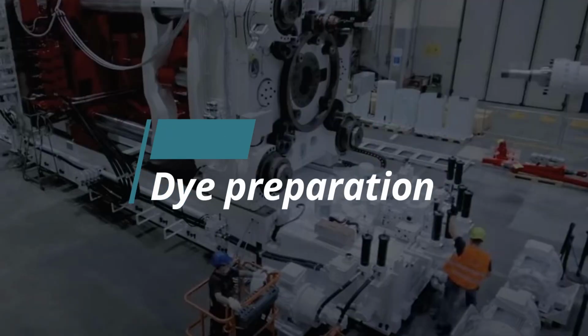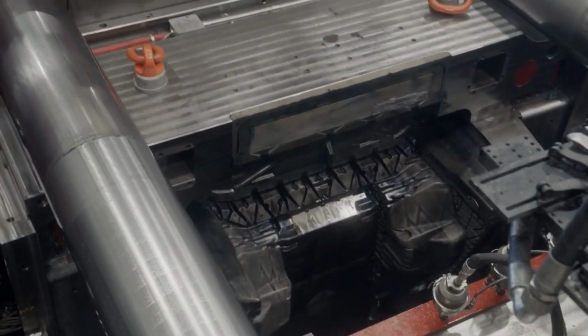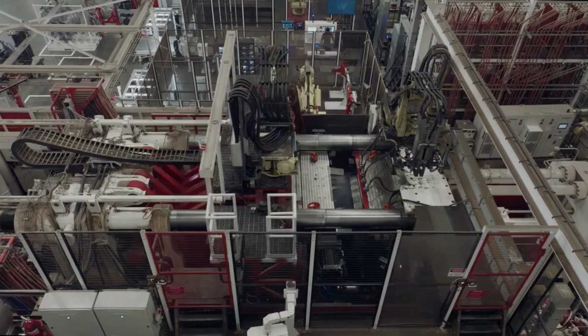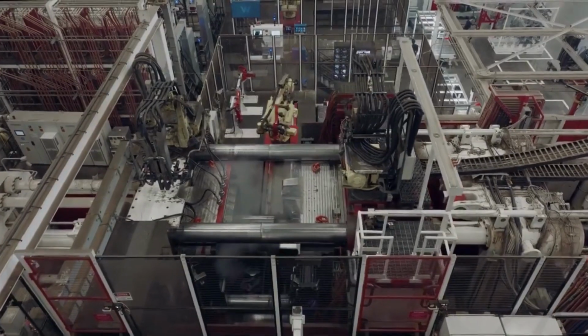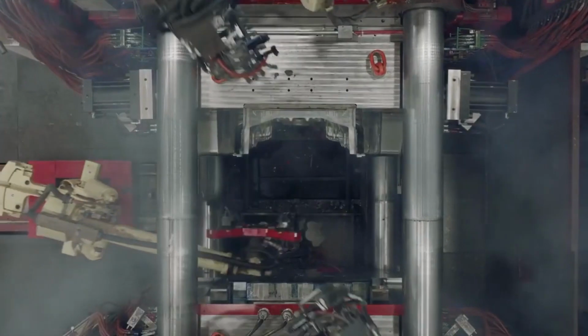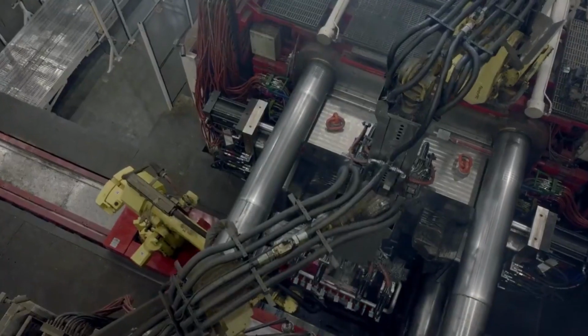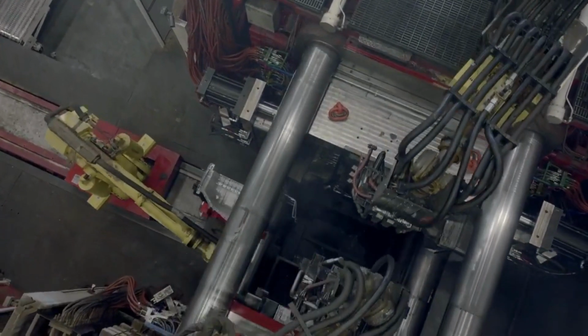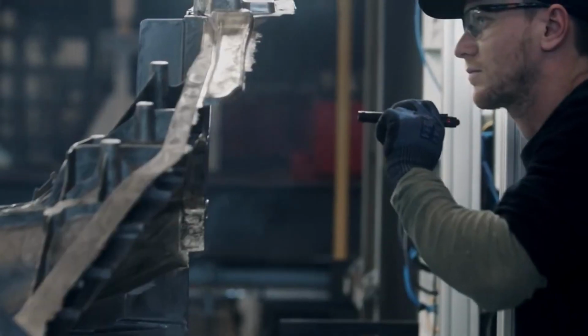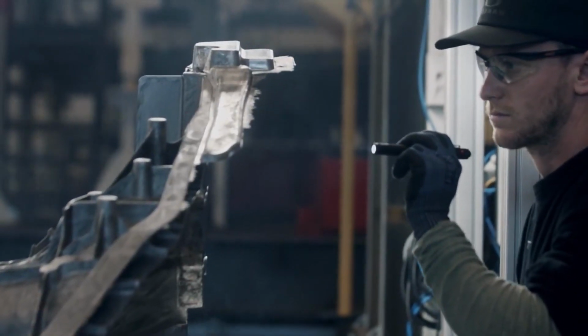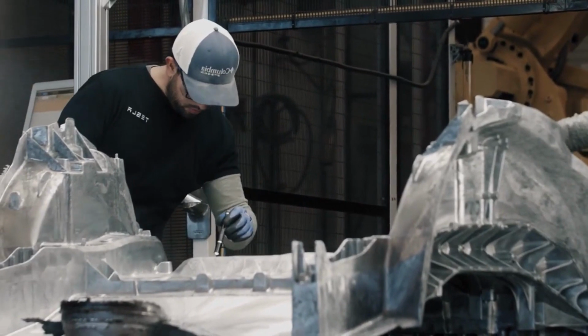Die preparation. Ensure that the die surfaces are lubricated before starting each cycle. To make it simpler to separate the casting, a robot sprays a thin layer of around 35 milliliters of soybean oil. The vacuum system then generates a vacuum pressure of approximately 50 millibars inside the mold cavity.